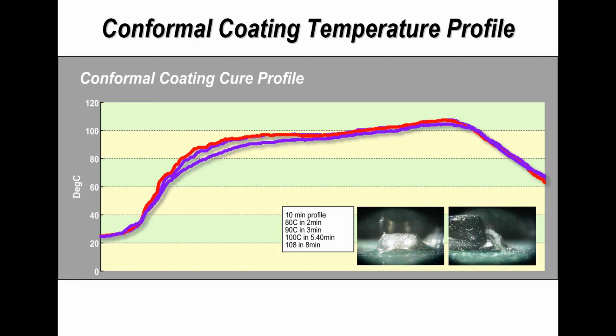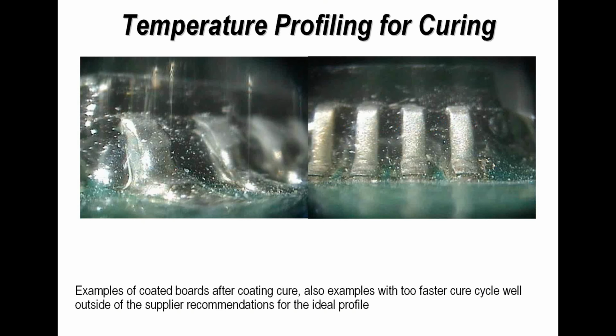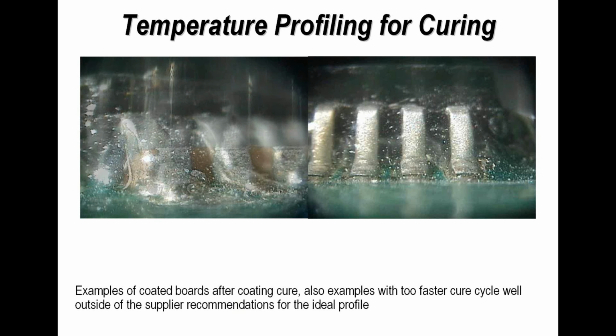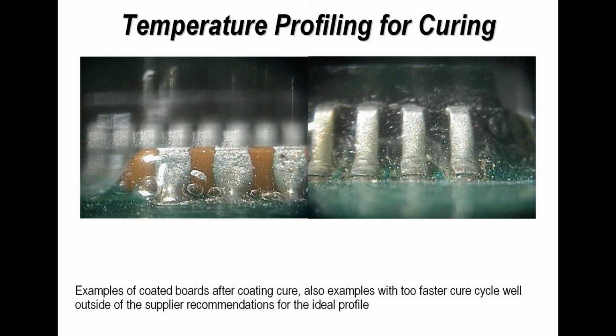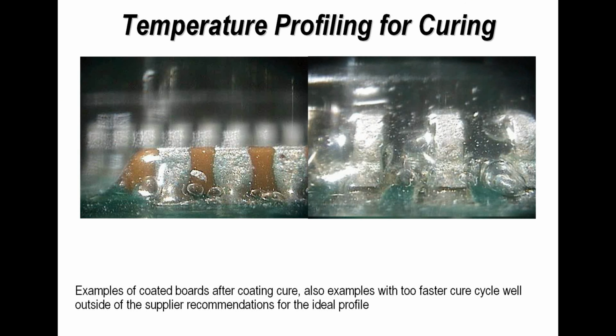If you cure it too fast, what can happen is you'll form bubbles, and that's something you want to try and avoid. And just an illustration, some photographs I have here. This is a coating. It's quite a thick coating, as you can see. But if I were to speed up the curing of this coating and show you photographs of this, what you'll actually see is a lot of bubble formation. So you can see bubbles in the coating between the termination on this resistor network, and you can also see it between this SOIC. So something that we need to avoid during our curing process.